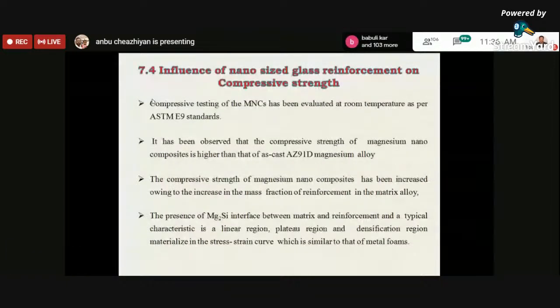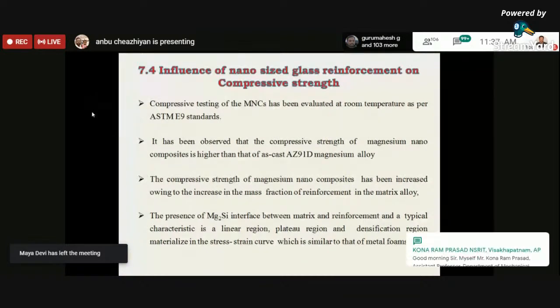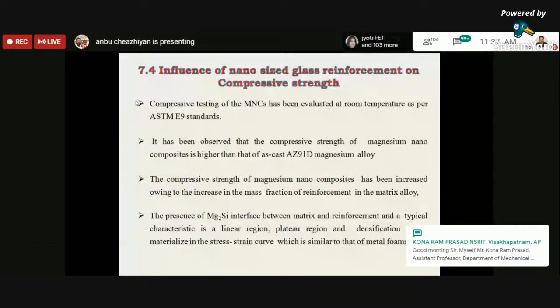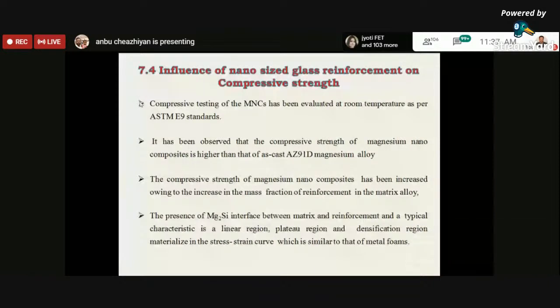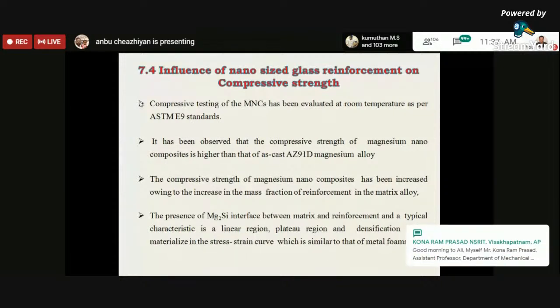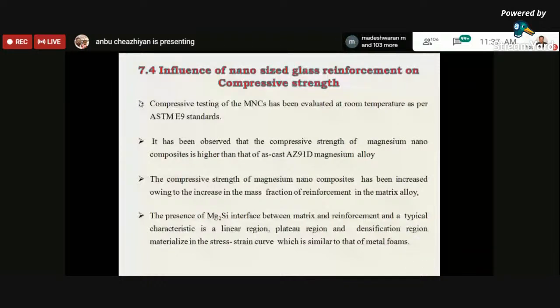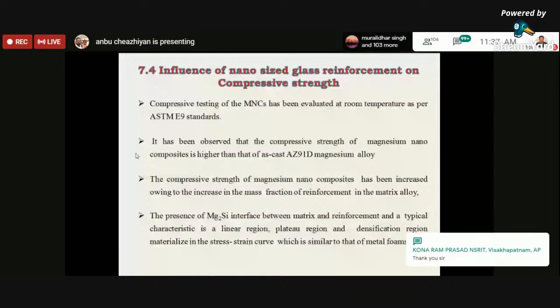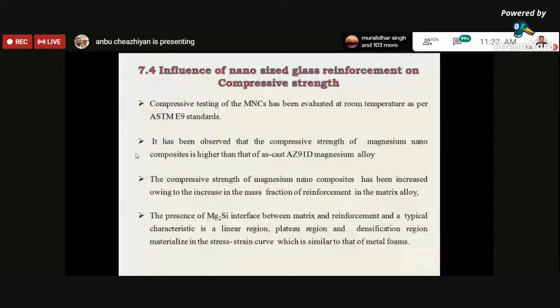Now the compressive strength of the nano-sized reinforced composites. As per ASTM E9 standards, the compressive strength test has been performed. It has been observed that the compressive strength of magnesium nanocomposite is higher than that of as-cast magnesium alloy. The compressive strength of magnesium can be increased due to increase in mass fraction of the reinforcement in the matrix alloy. As I told you, the presence of Mg2Si at the interface with the matrix increases the mechanical properties.